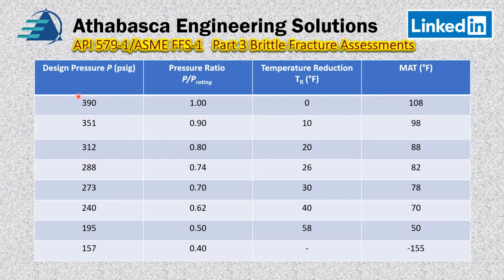We've constructed this curve. We know that the maximum pressure for this unit is 390. So the pressure over the rating pressure is 1.0, and here there's no reduction, of course, and we have our original 108 degrees Fahrenheit, which we found from curve A and also from what they told us in the example. And then we based it upon a nice number like 0.9. So if I took 0.9 times 390, I get 351, and so on all the way down this list. And then I go to that curve earlier, and we find our reduction factor. So then we just subtract from that 108, subtract 10, and we get 98, and we continue down.